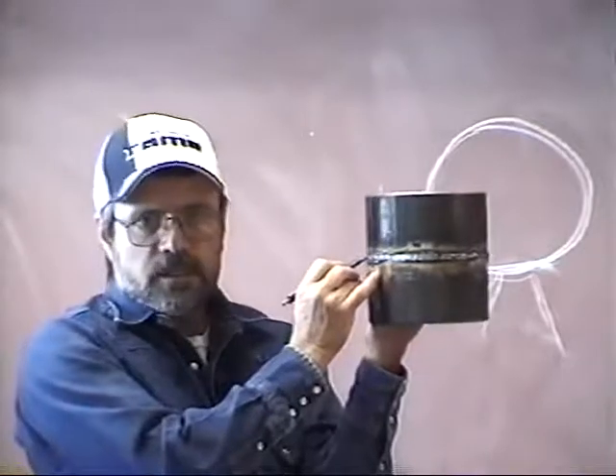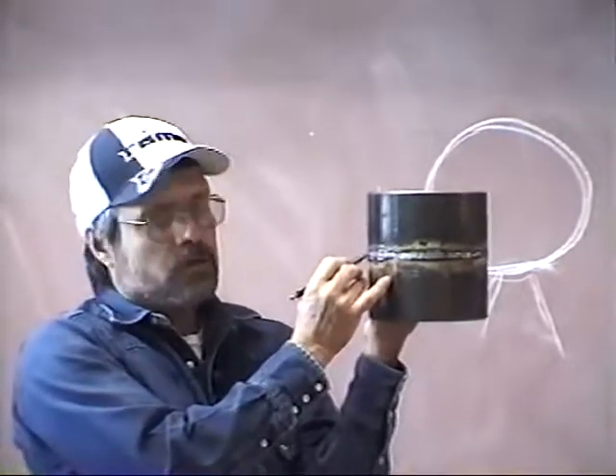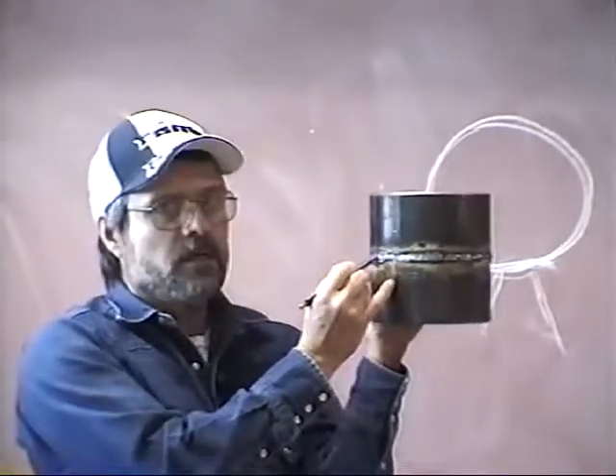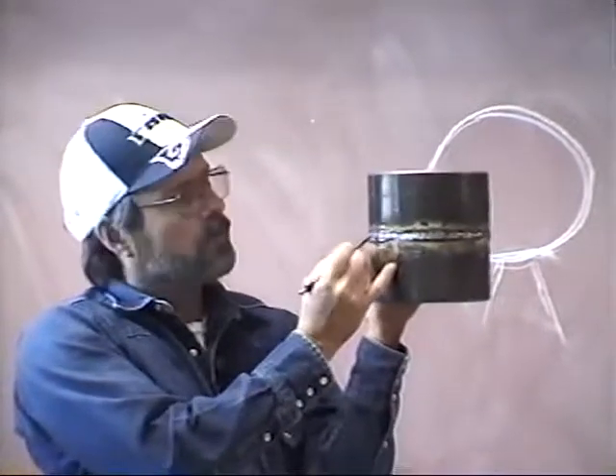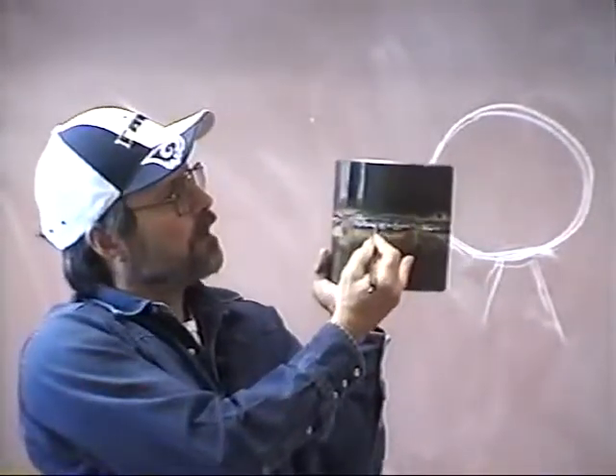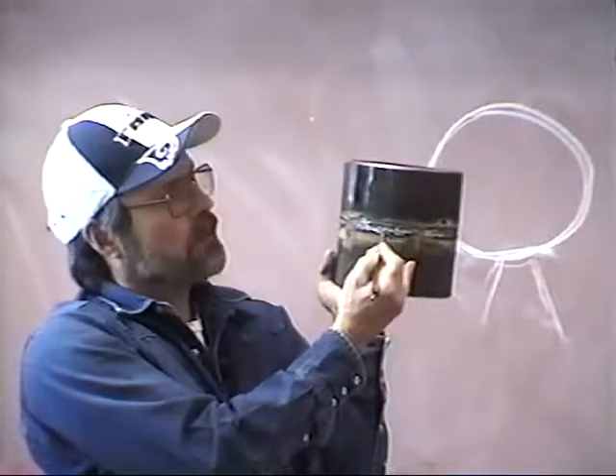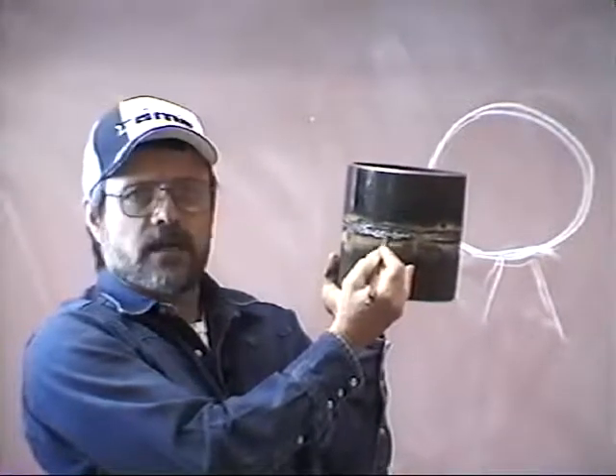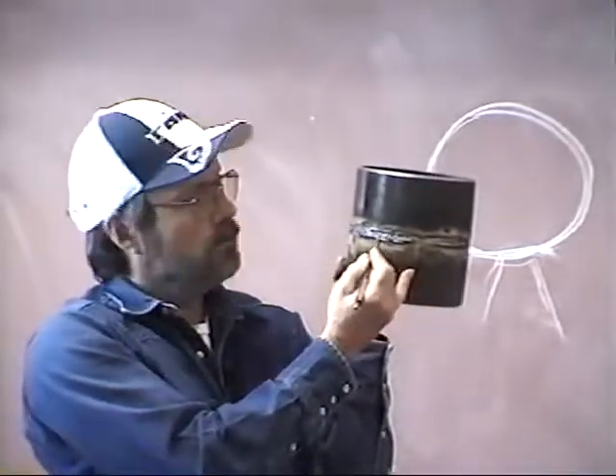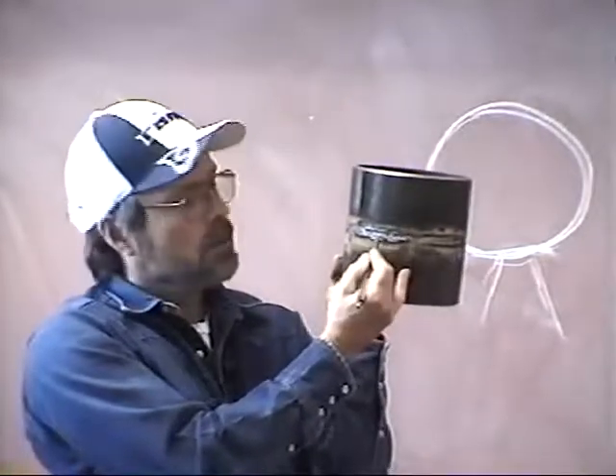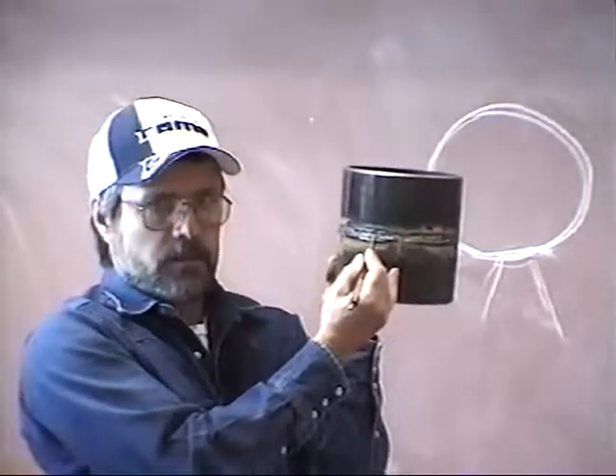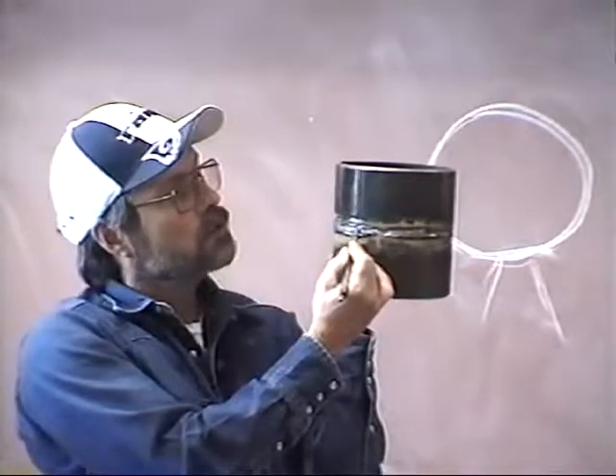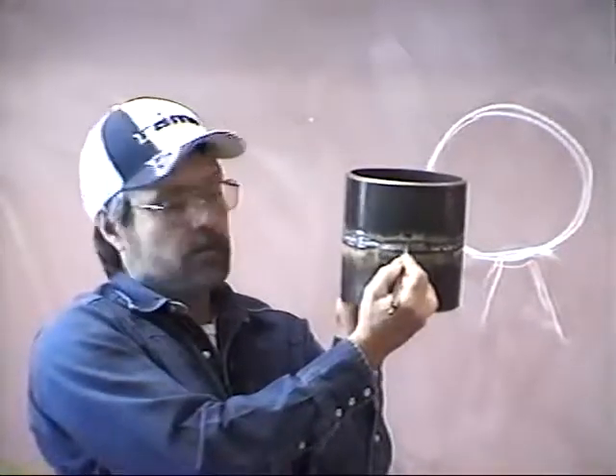If that keyhole starts to get too large, as he said, you can sometimes go ahead and increase your speed, but that may not always solve the problem. At that point, you might want to try using a whip. Just straight out and straight back. Don't try to chase the keyhole from side to side, because that's only going to enlarge the keyhole. But use the whipping motion out and back until it gets back to the size that you want. And then just go back to your drag technique again, like so.